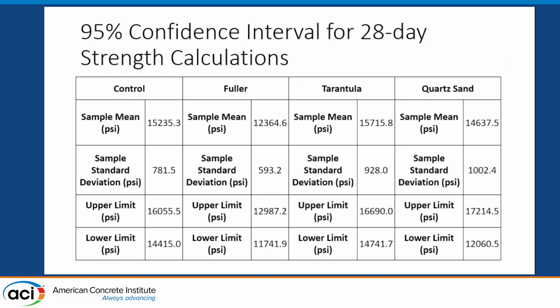So this is the 95% confidence interval that I calculated for each of the mixes with respect to strength. The highest average was the tarantula mix in this third column with about 15.7 KSI, and the quartz sand mix had the highest 95% upper limit with about 17.2 KSI.